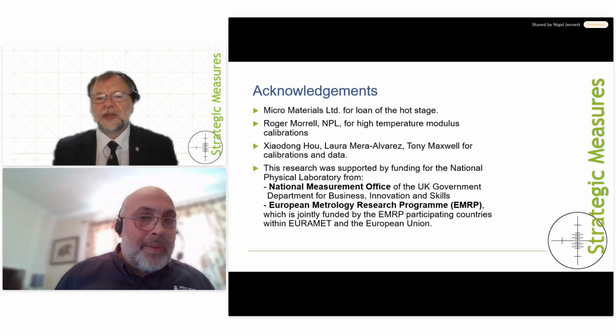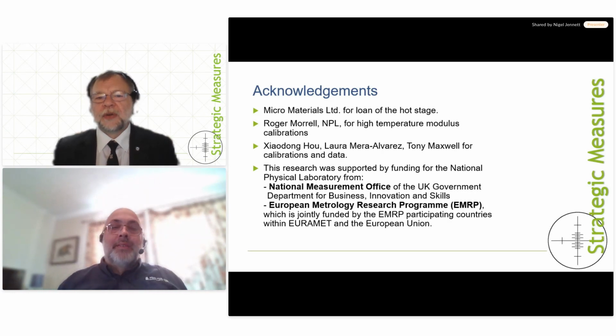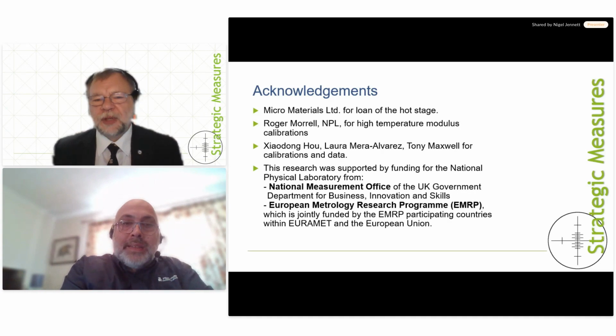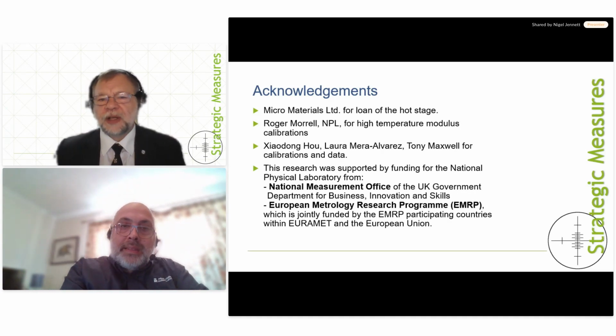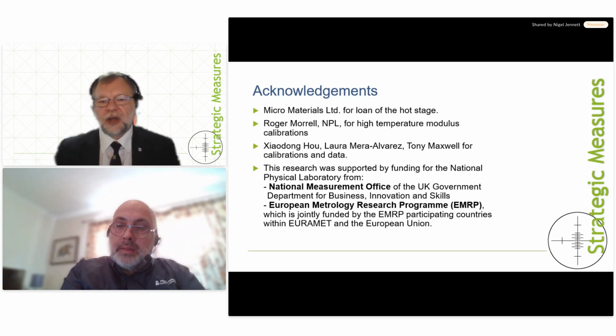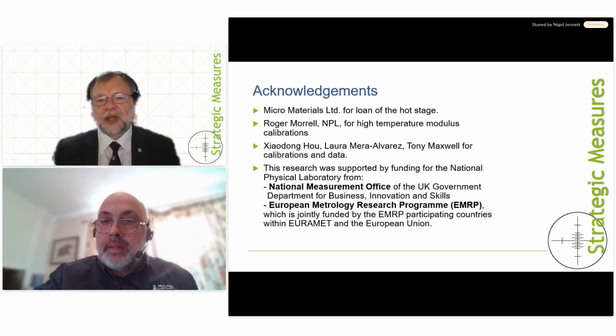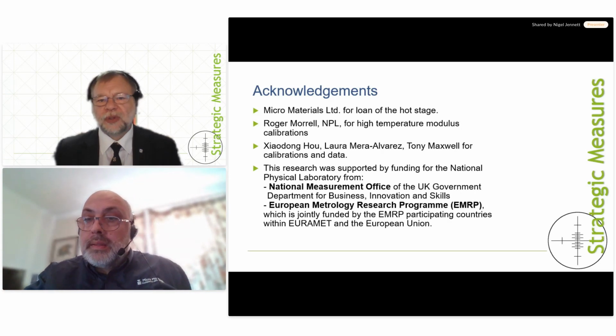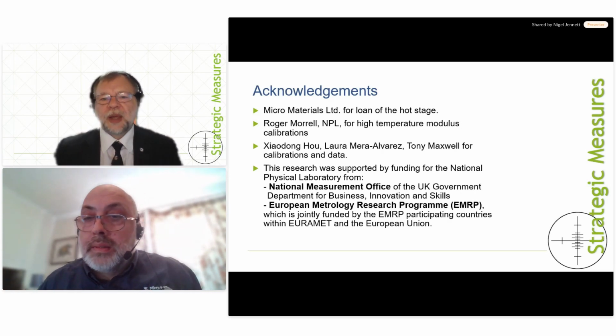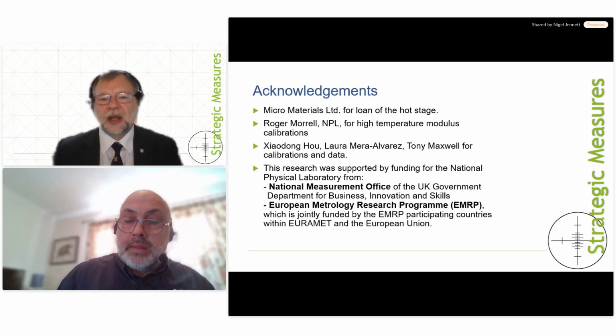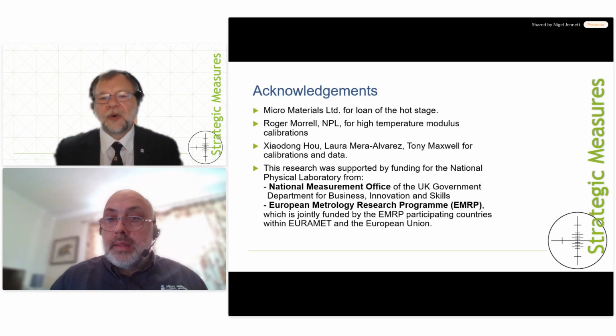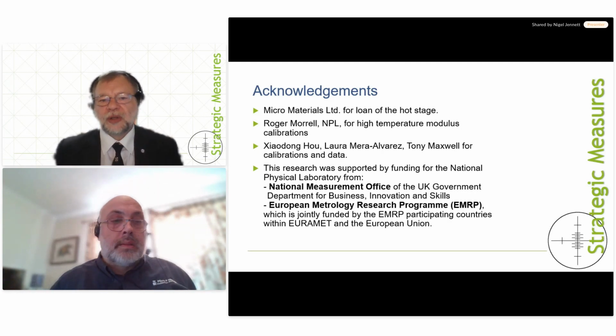I think that's reference material values. So I think interpreting that question is, are reference material values limited to a particular load and temperature, just like Vickers testing. Well, the difference between instrumented indentation testing and conventional hardness scales is that conventional hardness scales allow you to test at a single force. Instrumented indentation makes a virtue of being able to test at a continuously increasing force and make measurements of displacement all the way along, and then you can choose where you stop.